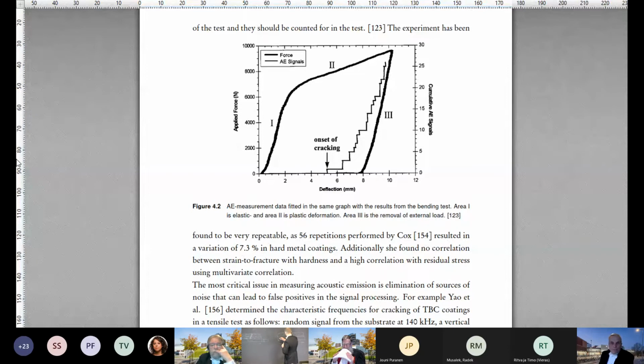This part would bend for sure since it's metal. This part would want to bend, but it might resist a bit. So we would see delamination here. And afterwards, probably some V cracks as you have a crack coming and the coating gives in. But as to when it starts, I think it would be, hopefully, before tension. In that case, it would be more damage tolerant in tension, I guess. But it's interesting. I think it's a good question because a lot of your experiments, in fact, produce compressive stress states. Well, they are a mix of everything, but nevertheless, it's compression in a lot of cases. So it's a good point.